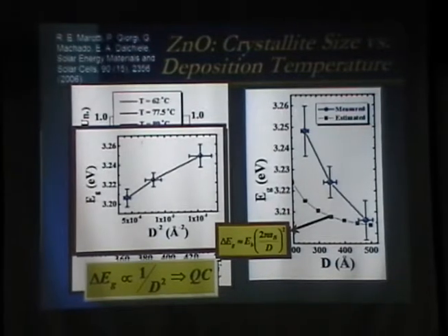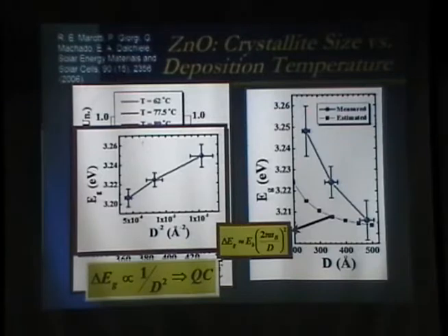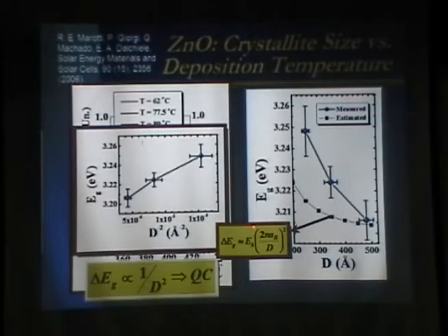The absorption is measured from the optical properties. The smaller crystallites enhance the optical properties. So in the optical properties, the smaller crystallites are more important, while in the X-ray diffraction, the larger crystals are more important. So at this point, we are mainly measuring some mean in a distribution of sizes that we have in the material.